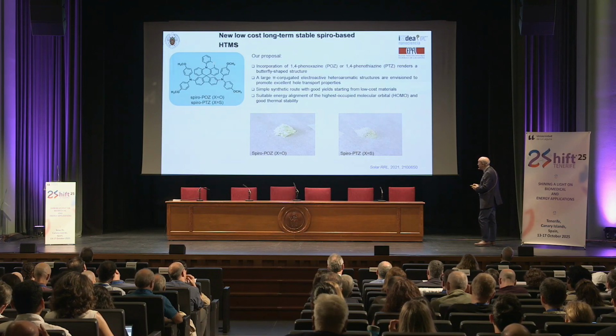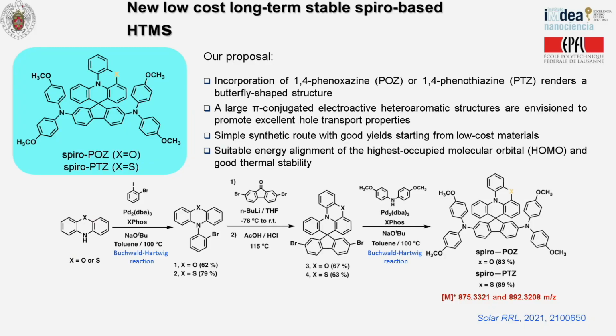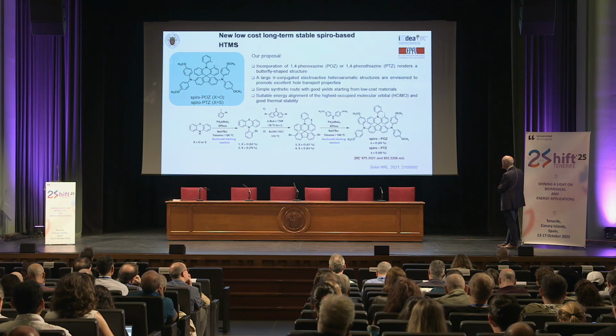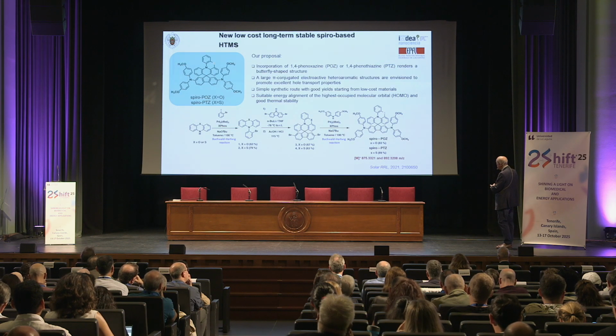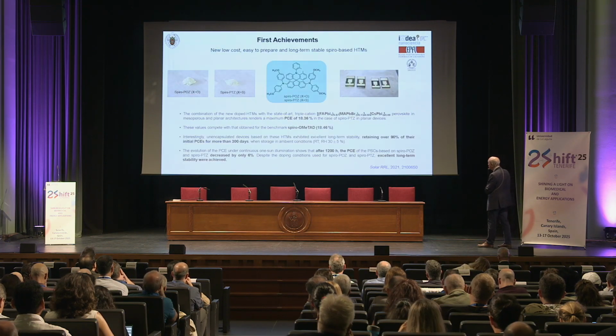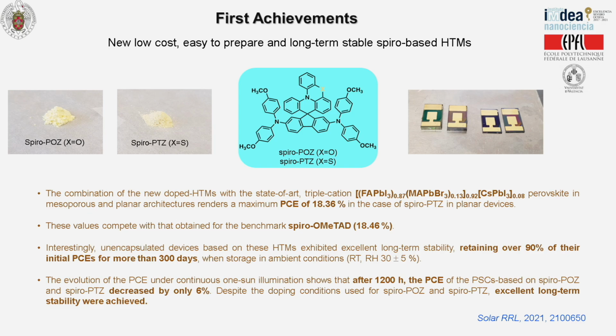And this was synthetically relatively simple to do because you can see here that from this commercially available phenoxazine or phenothiazine, you can follow this interesting chemical reaction, but in 3 steps you can get this material. Okay, it was fully characterized. I will not go into details. And these are the cells we prepared in our lab at the Institute of Nanoscience. And you can see we did it with a triple cation perovskite with efficiency of 18.36.